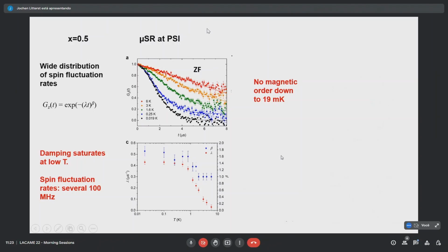What we also see is the damping of the muon signal. If you go down in temperature, the damping becomes stronger. Stronger damping means the magnetic correlations are getting stronger and the fluctuation frequencies are slowing down. It's plotted down here, that only follows the red curve here. That's a logarithmic scale. You have a slowing down here at high temperature, but then below 1 Kelvin, it suddenly turns over and saturates down to low temperature. So these fluctuation frequencies, which are on the order of some 100 megahertz, persist to lowest temperature.